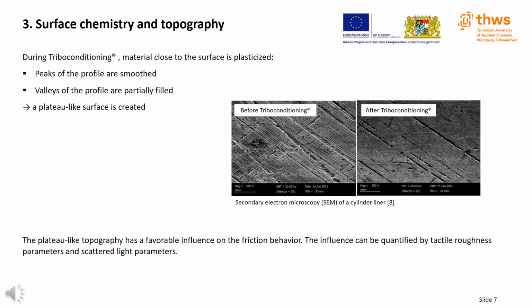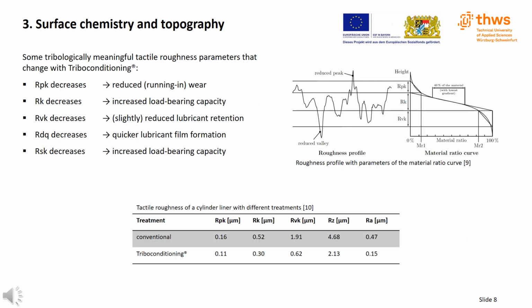The influences can be quantified via tactile roughness parameters and scattered light parameters. On this slide, I will present some tribologically meaningful tactile roughness parameters that change as a result of triboconditioning. First, I would like to briefly discuss the parameters from the material ratio curve, which is also called bearing area curve or Abbott-Firestone curve. On the right, you can see an exemplary roughness profile with the corresponding material ratio curve. By graphical construction in the material ratio curve, the reduced peak height RPK, the core roughness RK, and the reduced valley depth RVK can be derived.